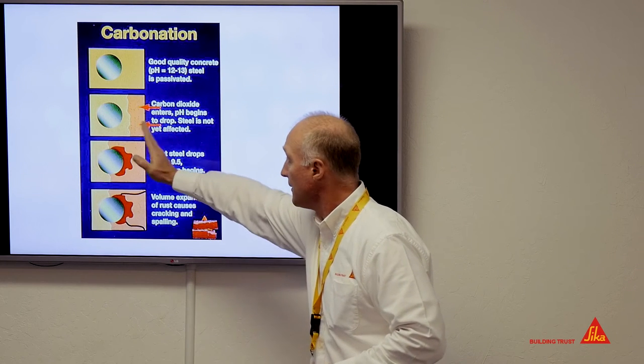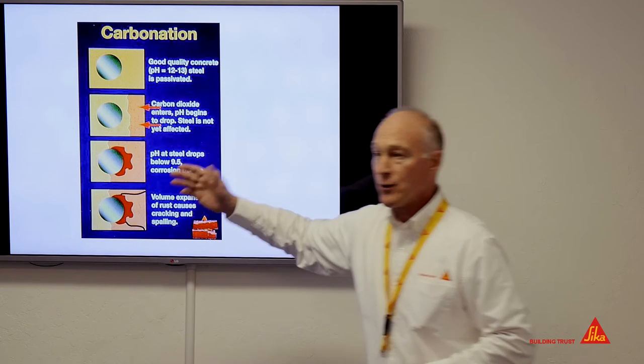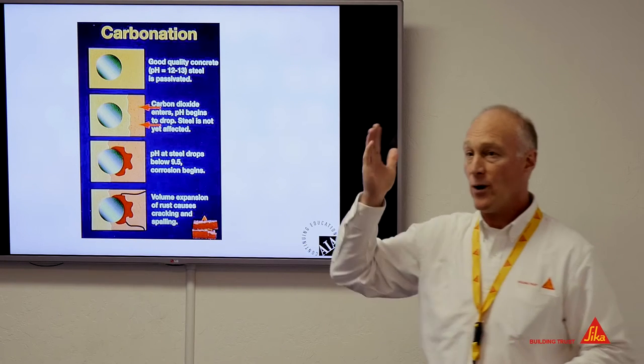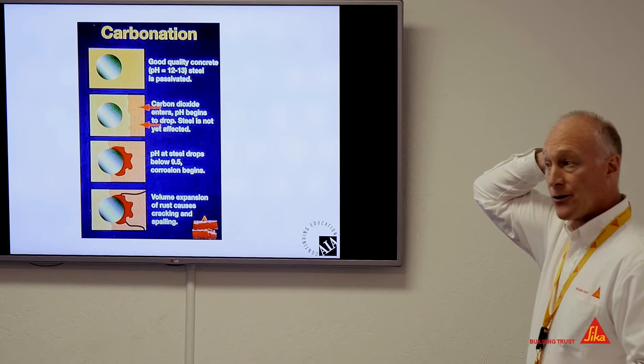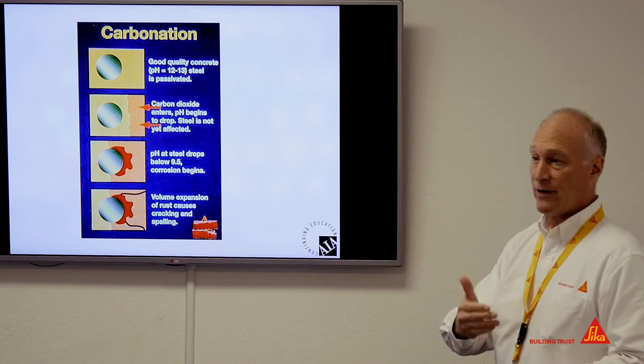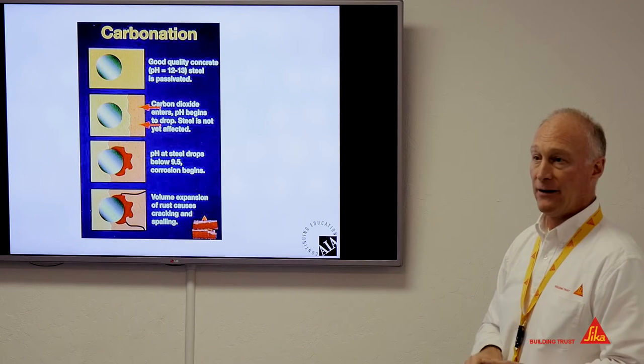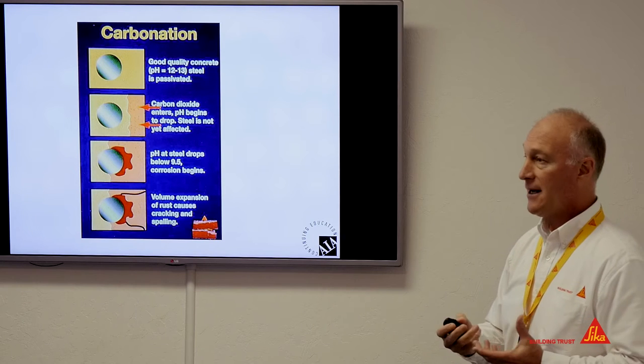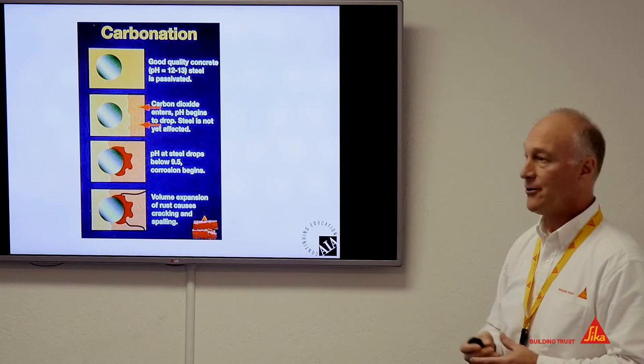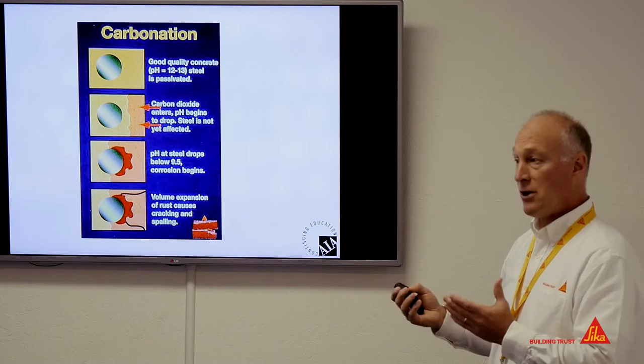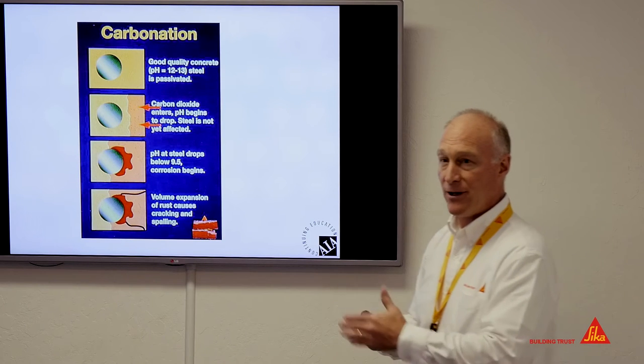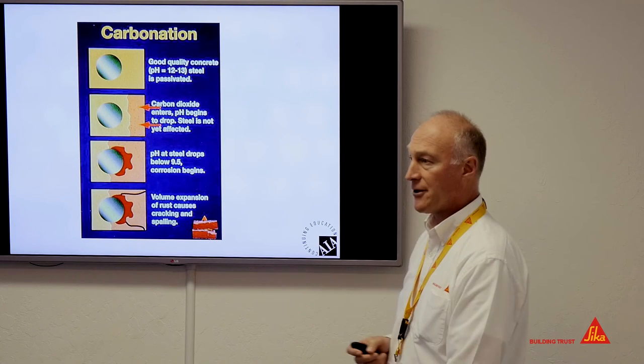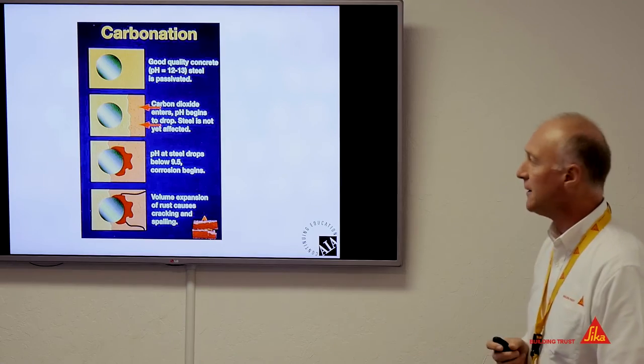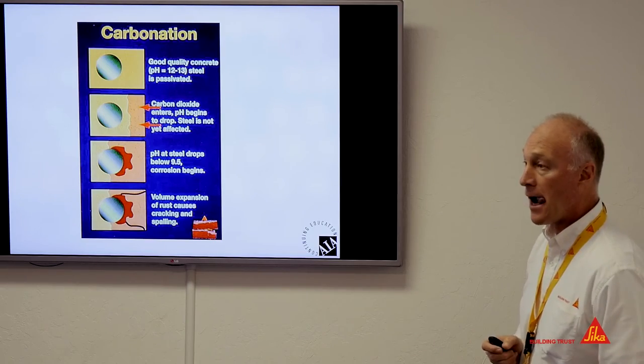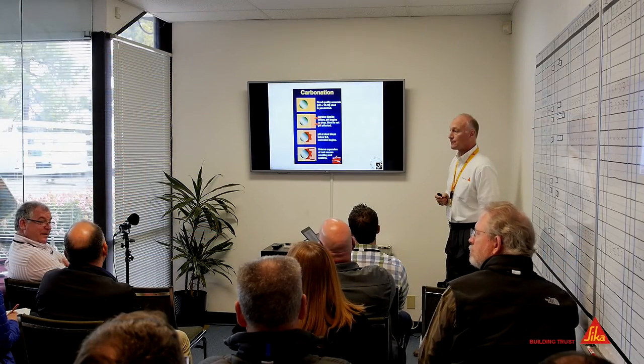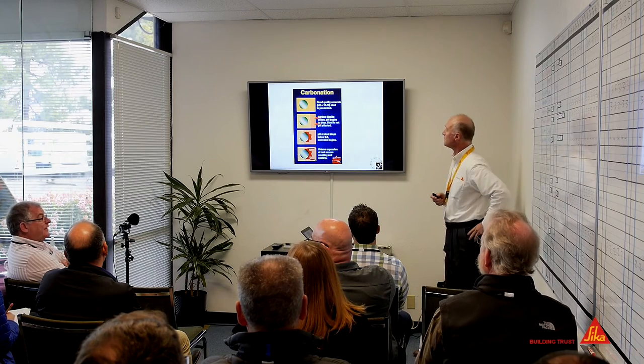You can see this. I've heard figures where this will penetrate concrete at a rate of 1 millimeter per year. So that's almost an inch every 25 years. If you think about the structures that we're talking about today, these structures are 70, 100 years old. So you would expect the carbonation to be 3 to 4 inches into the concrete on a structure that's 70 to 100 years old. But you also add that it will quicken with moisture. Moisture will carry the CO2 through quicker.